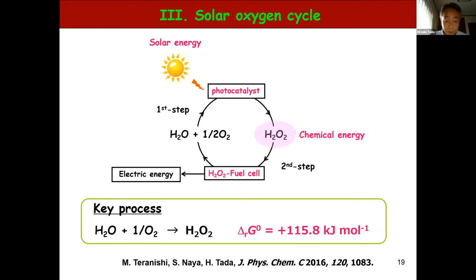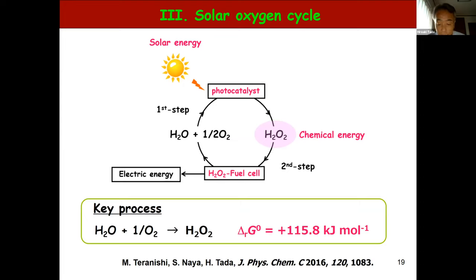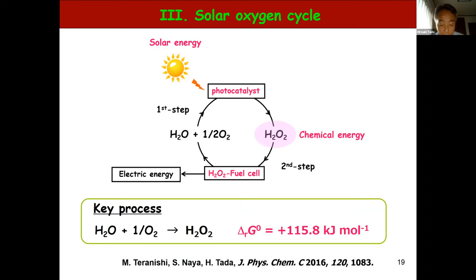Let me move to the third section on the solar oxygen cycle, involving the synthesis of hydrogen peroxide from water and oxygen as the key process. This reaction is also energetically a large uphill reaction, and utilization of thermal energy as the driving force is impossible because hydrogen peroxide is easily decomposed by heating. When using light as the energy source, thermodynamically this reaction can be driven by photons with energy larger than 1.2 eV. If we can photocatalytically produce hydrogen peroxide, input into a hydrogen peroxide fuel cell generates electric energy to complete the solar oxygen cycle.